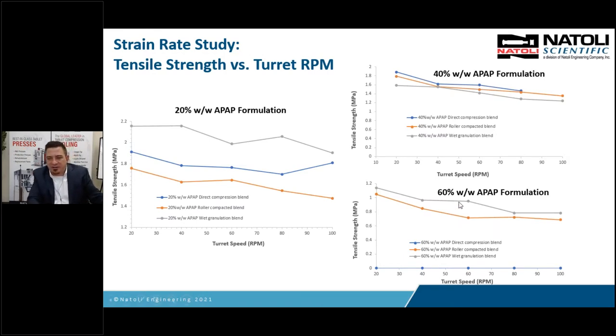And then we look at the 60%. It's dropping as well. There doesn't seem to be a huge difference between 20, 40, and 60 on strain rate sensitivity, but the material definitely is strain rate sensitive, and you do want to be careful when you go from R&D into a higher speed pilot scale production press.